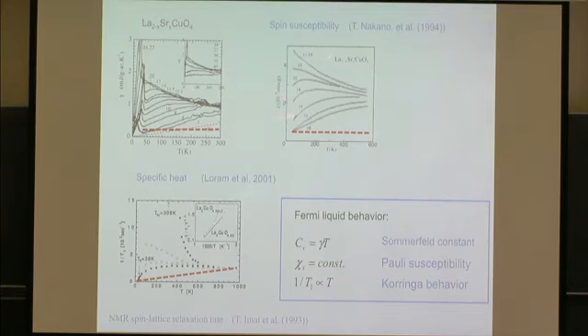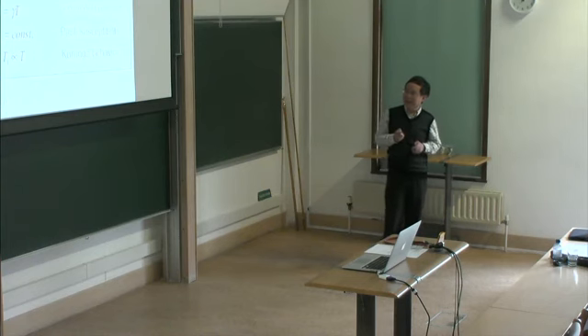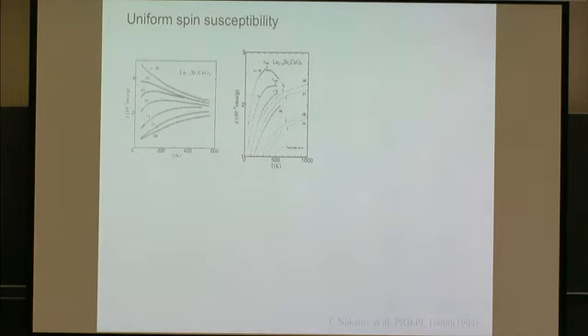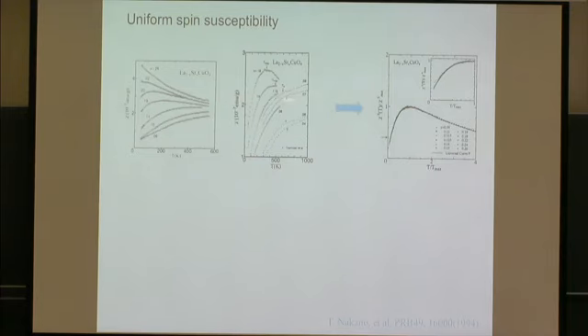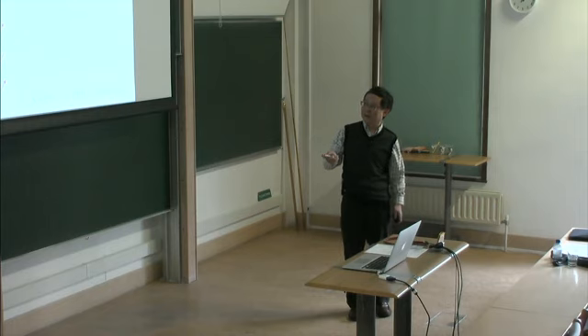And this is the spin susceptibility at different doping, and this is the 1/T1 NMR relaxation rate. Let's focus on the uniform spin susceptibility for the 214 material. This is at different doping, and this is underdoped, and all this data shows you cannot see any trace of Pauli susceptibility. In fact, this data can be rescaled into some kind of universal curve. This is slightly data massaged, but nonetheless you see the temperature scaled with the peak value temperature, and the susceptibility divided by the maximum value. And this universal curve is not like a Pauli susceptibility contributed by the quasi-particles near the Fermi surface.